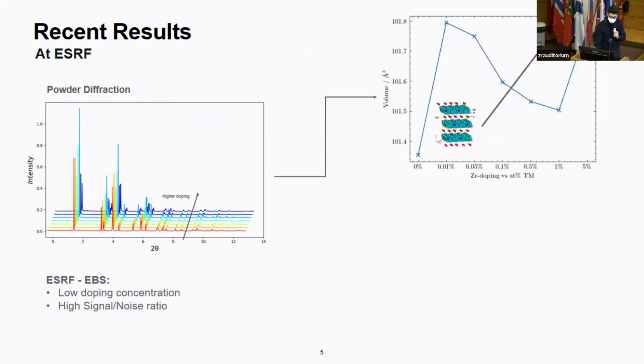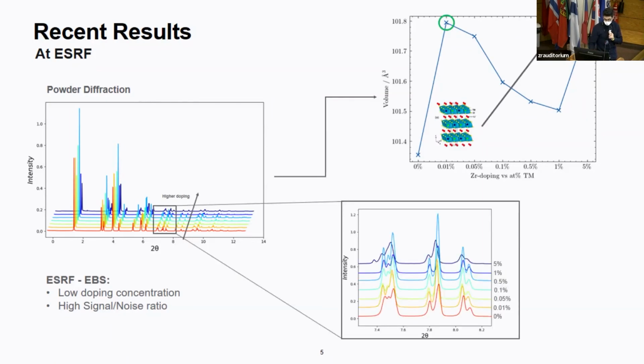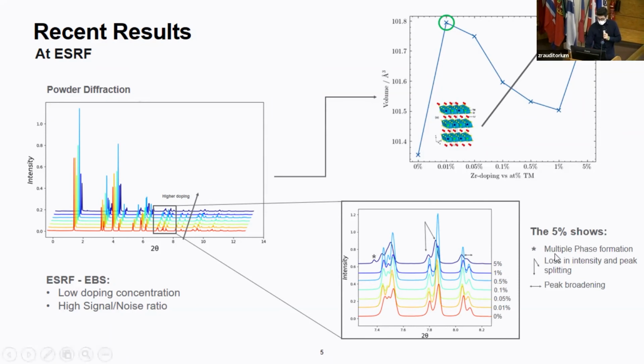When we analyze this data, we see that as a function of the doping, the unit cell is enlarging, expanding. If we look at the 5% doping, the highest doping concentration, compared to the lowest one, we get a similar expansion of the unit cell. However, when we look at the features of the 5% in the powder diffraction, we see things that we cannot see in the other samples. We have multiple phase formation, we lose intensity, the peak splitting is not as well defined as in the other samples, and the peak broadening for the 5% is higher compared to the other samples.